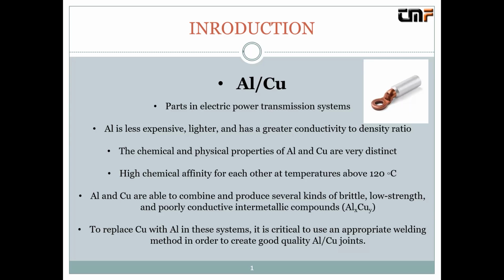During the investigation, we faced a lot of problems. First of all, the chemical and the physical properties of aluminum and copper are very distinct. Chemical affinity between those two elements is very high. In that manner, there is a tendency that aluminum and copper form a lot of different intermetallic compounds. We used this designation AlxCuy, and you will see the reason for that kind of designation. So it was critical to use an appropriate welding method in order to create a good aluminum-copper joint.